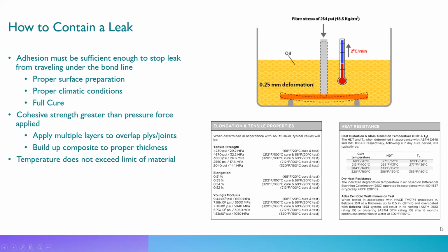And then there's also specific heat distortion and heat resistance testing that you can do. HDT, heat distortion temperature, is one of the most popular and common. This is where you have a cast sample and you put it in an oil bath, put a constant load on it, and you raise the temperature until you see some deformation in the sample. That's when you know that you're starting to lose some mechanical strength. So we've got to understand, at this temperature, how much mechanical strength are we losing? Then we look at the pressure and say, hey, we're going to have enough strength at that point to contain this leak long term.